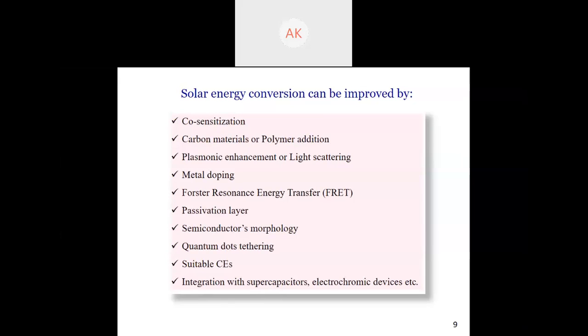Third, there can be plasmonic materials which show plasmonic enhancement or light scattering. Metal nanoparticles such as Au, Ag, Cu, which have dimensions less than 50 nm, show mostly plasmonic effects, and more than 50 nm maybe light scattering. The main work of these plasmonic materials is that they enhance the absorption capability of the adjacent quantum dot. There are metal dopings, with literature on, for example, Mn2+. When you have metal dopings, electronic states get created in the mid-gap region, and this ultimately lengthens the lifetime of the charge carriers.